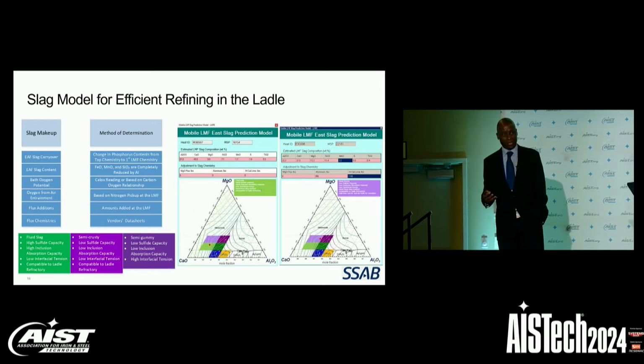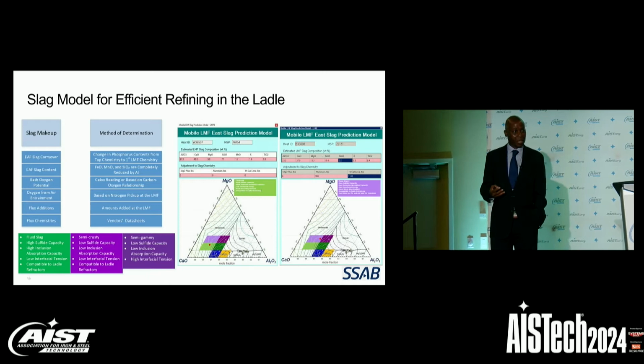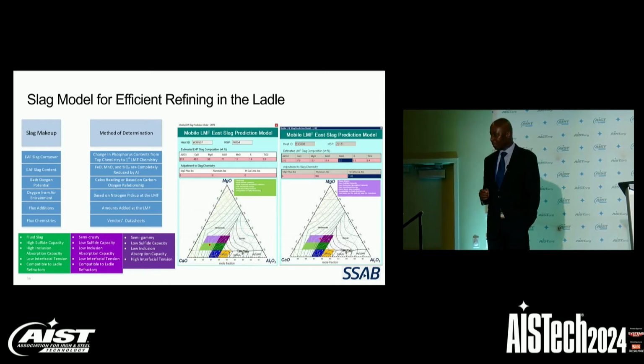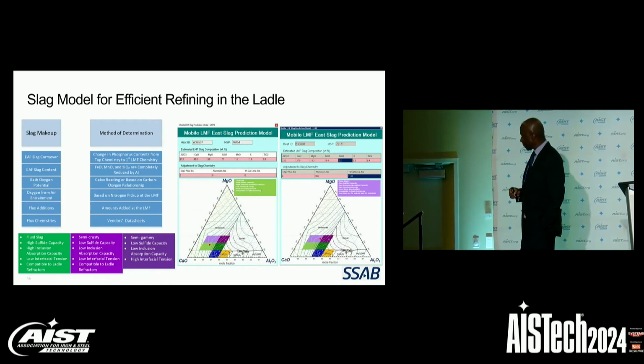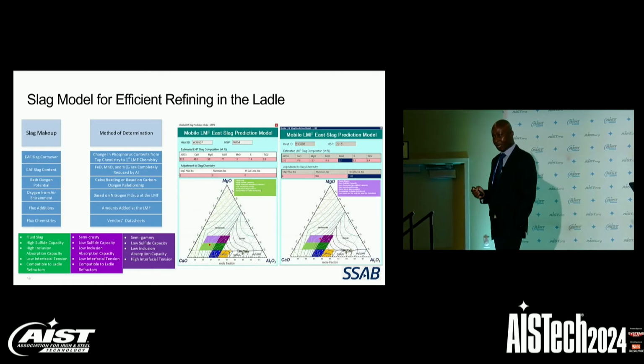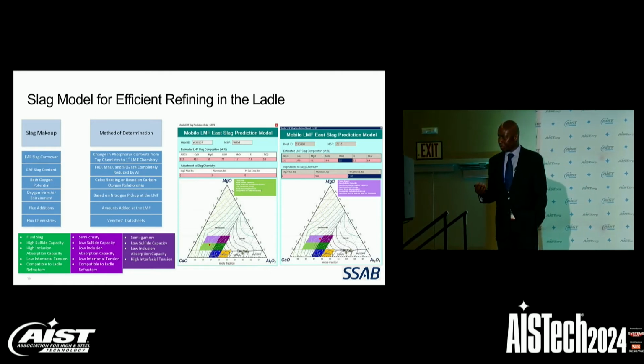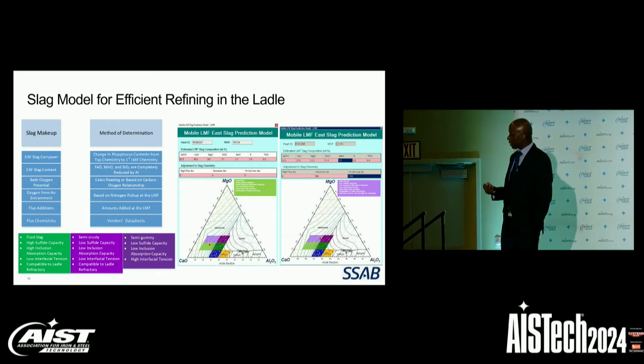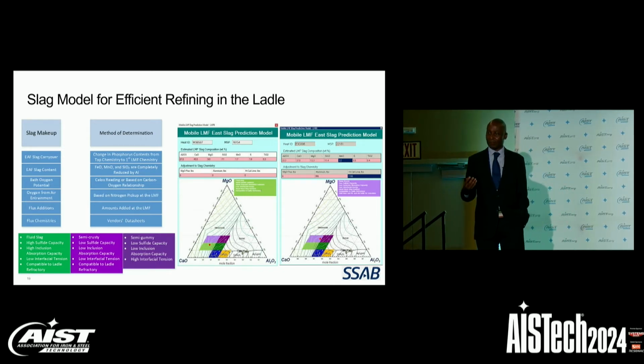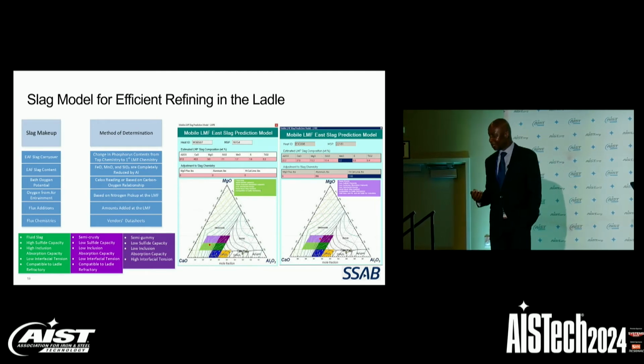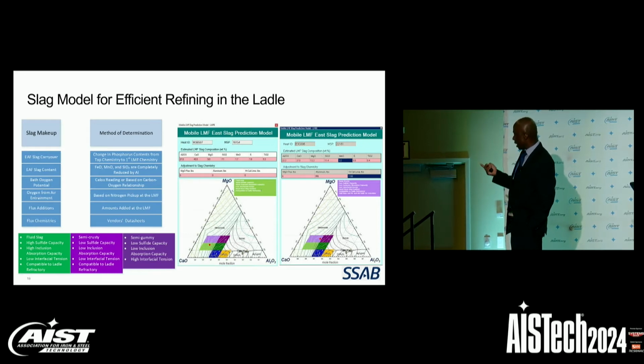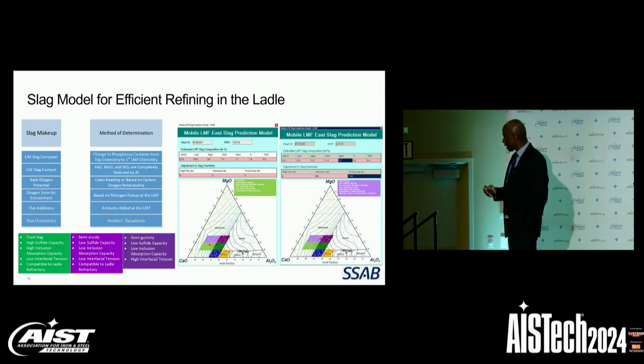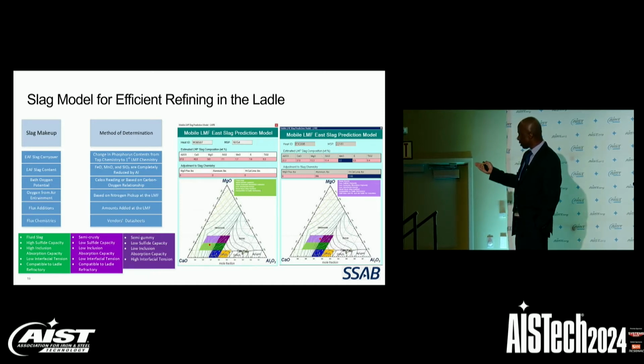Then we also consider the amount of fluxes and the chemistry of fluxes that were added during refining in the ladle. Then we look at historical data between the slag composition and the steel to understand how the slag composition affects sulfur removal. With that data, we're able to group the slag into various categories. We have fluid slag, high sulfide capacity; semi-crusted slag, low sulfide capacity; semi-gummy slag, low sulfide capacity, and so on.